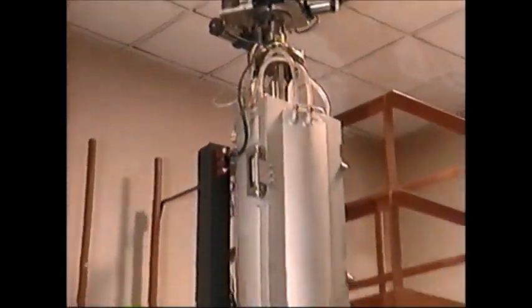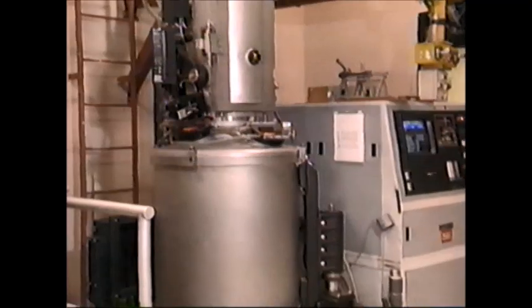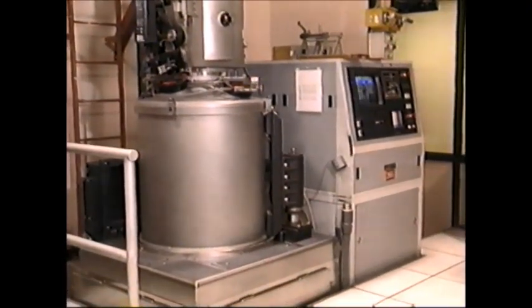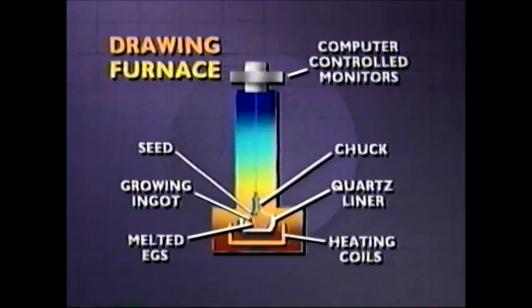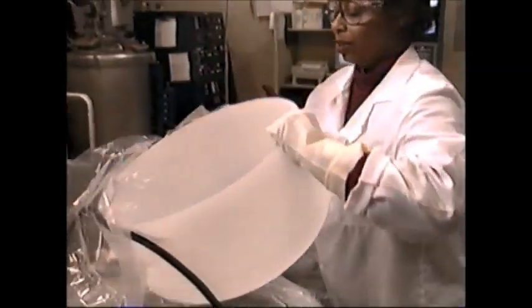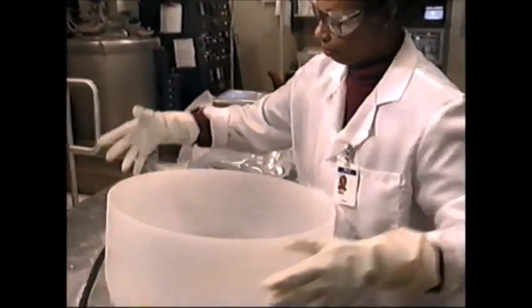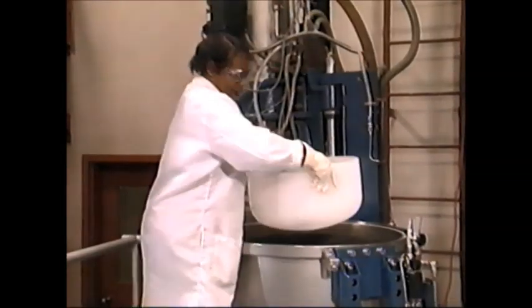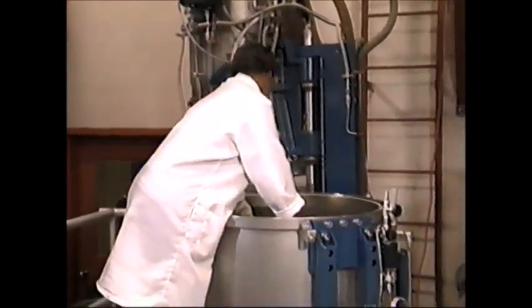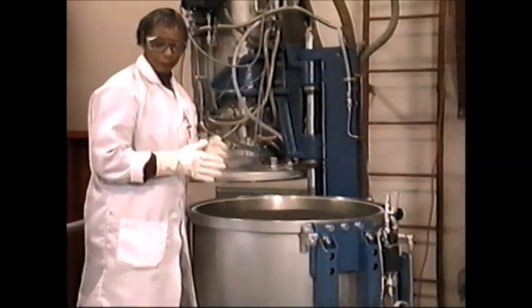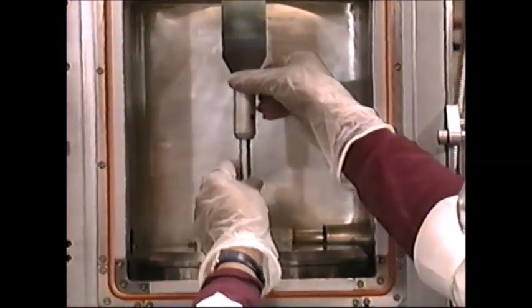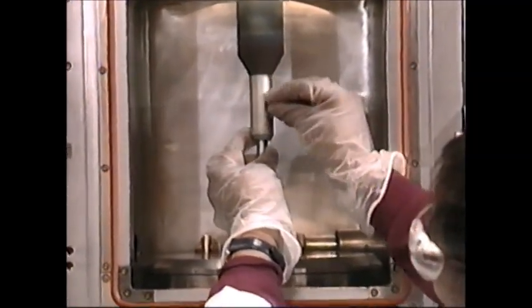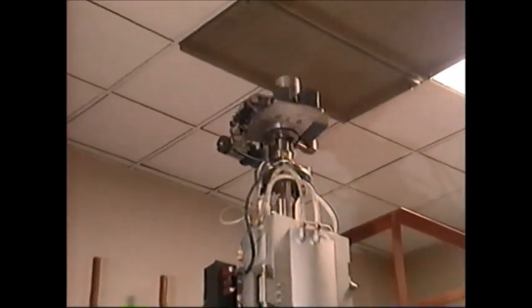Most manufacturers use vertical furnaces that work on the CZ or Czochralski crystal growing method, commonly called crystal drawing. This crystal drawing takes place in an electric furnace which will reach temperatures greater than 2,500 degrees Fahrenheit. The quartz crucible that holds the ingot ingredients must withstand the tremendous heat of the melted silicon. The quartz liner holding the charged mixture is placed in a carbon bowl or susceptor, which is then placed in the furnace tank. A small piece of seed silicon is attached to a motor-driven molybdenum chuck, which is suspended on a stainless steel wire from a motor platform at the top of the furnace.